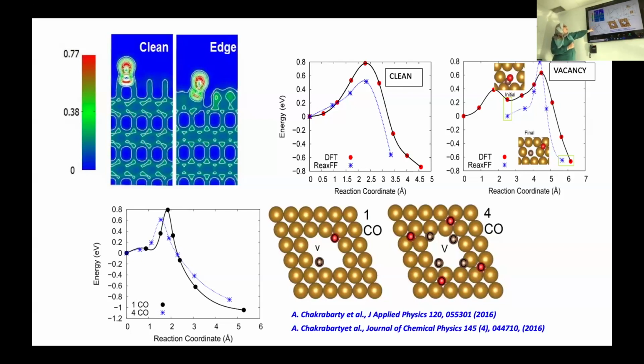So what we have done, this was done in collaboration with Noma and Charlotte, is that we took the DFT calculations and then we recomputed the diffusion pathway using the reactive force field. In the case of the clean surface, it reproduces the DFT results very reasonably. In the case of the vacancy, it was not that bad as well. There was a difference in terms of the initial energy in this case.